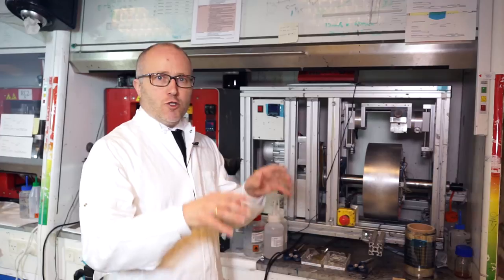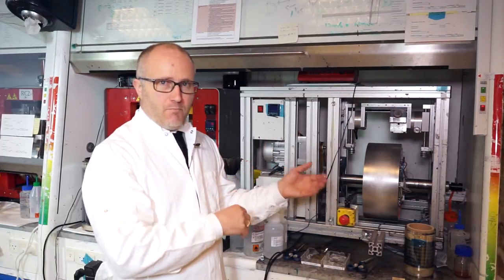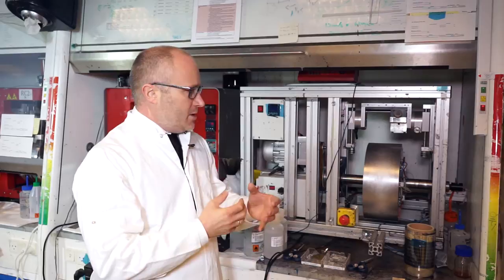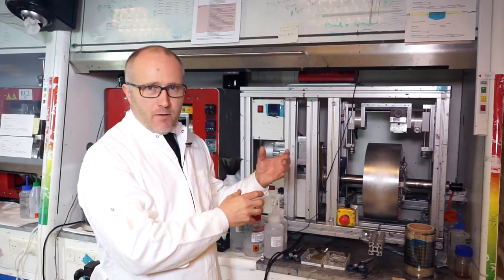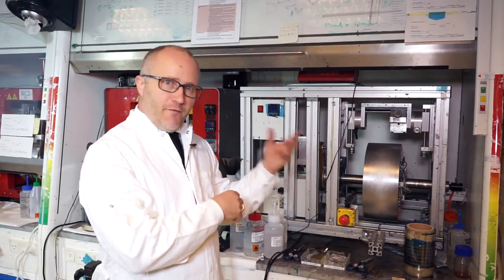The moment you go to a flexible foil with typically an insulating structure and some conducting structures on it, the static electric field becomes extremely critical. So what I wanted was to enable roll-to-roll processing on flexible substrates where we have removed the possible adverse effect of a varying static electric field on low viscosity inks.